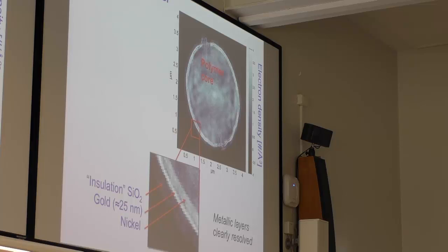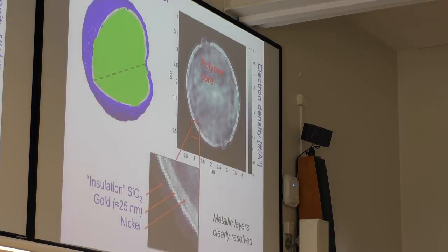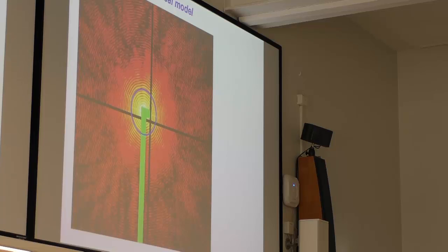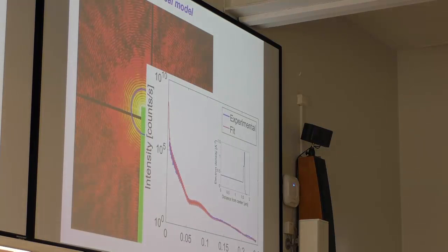study we have done on Ugelstad spheres, where you have a polymer core, and outside, in this case, these are particles from Conpart that maybe some of you know. It's a Norwegian company, where there is a nickel coating, a gold layer coating, and also an insulation layer. So this is resolved in 3 dimensions to high resolution. As you can see, we can clearly segment this to look at what is going on inside. And we can also just look at the scattering patterns and describe this analytically, because they are such perfect spheres,